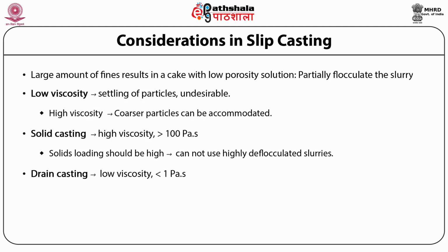Fourth, for drain casting, the viscosity should be low, that is less than 1 Pascal second, while it can be greater than 100 Pascal second for solid casting. And the last one is that binders are used to provide strength to the cast. Most often, clay is used as a binder. Organic binders of medium molecular weight or inorganic binders are also used. A mixture of binders can also be used instead of clays.